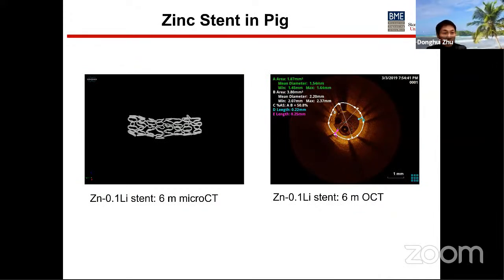We also did some preliminary study using a zinc-lithium alloy stent in a pig model. This is the micro-CT imaging as well as the OCT after 6 months. The stent looks like it's still largely intact, and the lumen remains open and pretty normal as well.